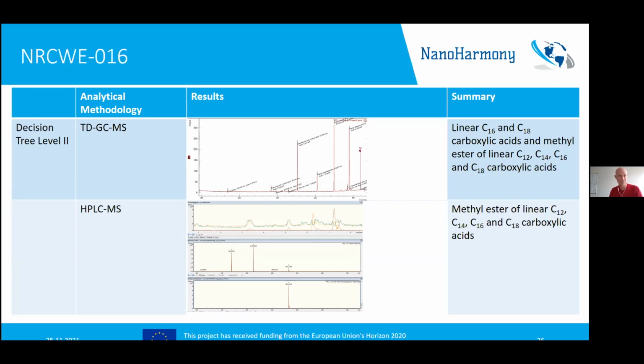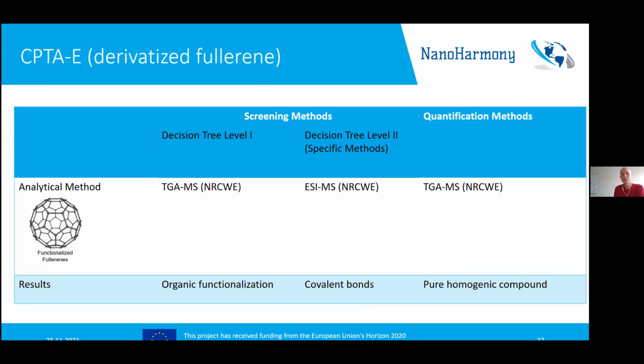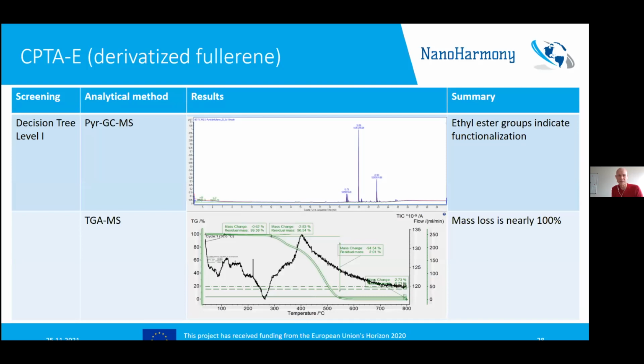We identify the different fatty acids and methyl esters coated with the LC and GC methods. And finally, for the fullerene, we had the challenge in this case that the core was organic and the side group functionalization was also organic. So this was a challenge, for example, for the TGA-MS, but we could use inert and oxidative conditions during the analysis to remove the side groups and detect their weight percentage of the whole material without ruining the structure of the original inert fullerene structure. That was possible with TGA-MS.